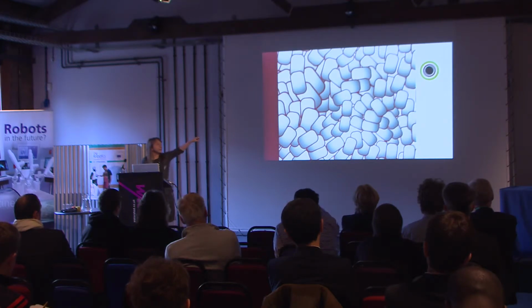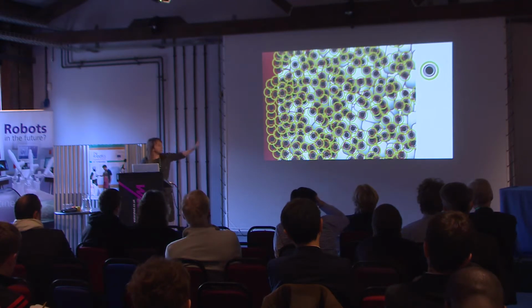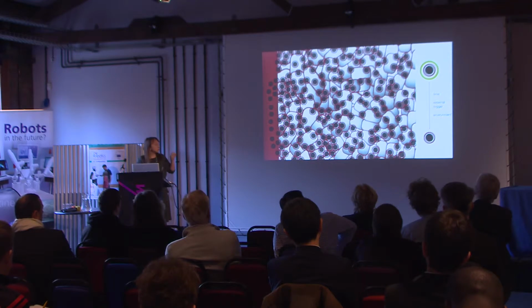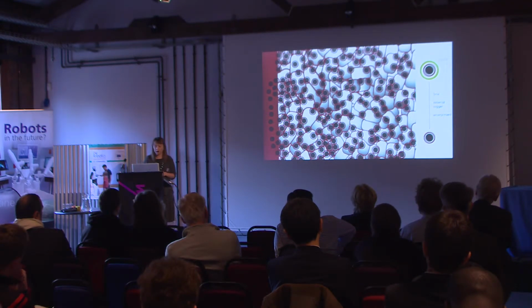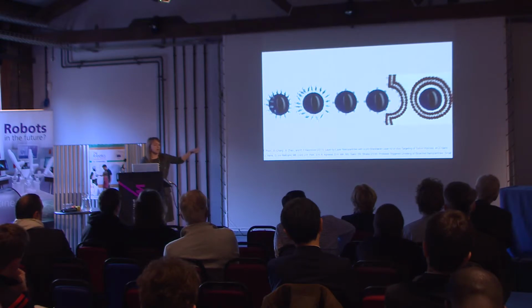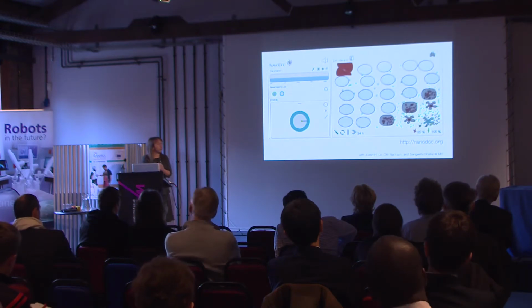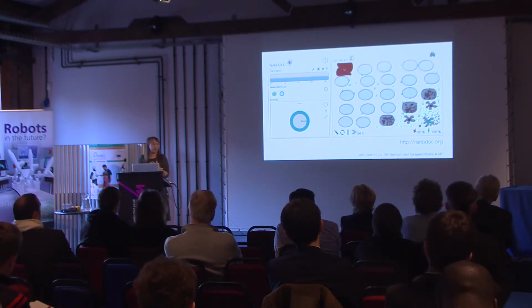So we said, why don't we prevent these particles from sticking, so we have a shell on them, and we let them go deep into the tumor tissue, take that shell off, and then they can finally stick to the cancer cells and get eaten up by them. It turns out that if you do that, you can solve for all the stickinesses, for all the sizes, the killing 20 cell problem. And there are actually particles that do this. This is a nanoparticle that was just a couple floors up from where we were that had this shell mechanism that could take off that shell, and they showed that it goes deeper into tumors. So that was great, but that was just one problem, spending 2 years thinking about nanomedicine.